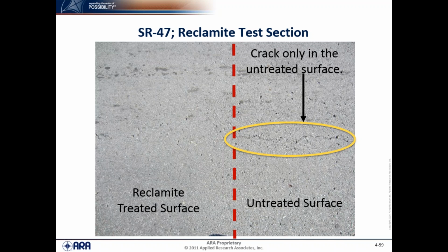But this was kind of a unique observation that the hairline crack could be observed in the untreated. When it went into the treated section, the crack wasn't there. And maybe below the surface, I don't know, because we didn't do any cores or anything like that. So it may be there below the surface, but you're not seeing it at the surface.